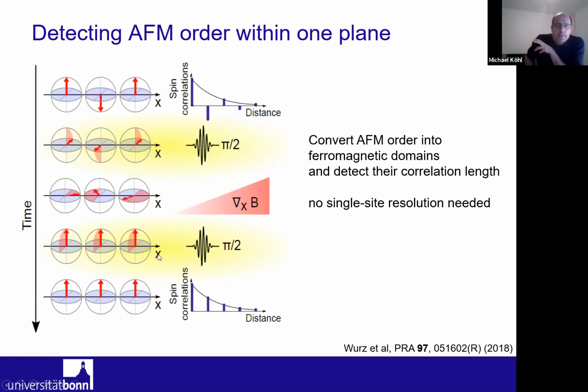We apply another pi/2 pulse, which flips the spins back into the same direction. And now we have converted this initially antiferromagnetic state into something which looks like a ferromagnet. And the ferromagnet is much easier to detect because with our imaging, we can just measure the sizes of the domains. And basically, we convert the measurement of the staggered spin correlation function into a measurement of a homogeneous spin correlation function. And by choosing the direction of the gradient and the strength of the gradient, we can measure this for any k vector in the lattice. For this experiment, we're particularly interested in the pi direction because this is where the antiferromagnetic correlations are. But we have also done this for other values within the Brillouin zone.